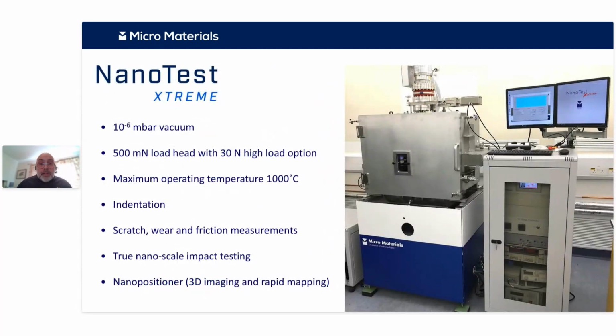That's a rather better picture of our system in the vacuum. Some of the work that you'll see today has been done in that. Some of that's been done on the Vantage system, often with the purge chamber option. But what I want to emphasize here is that it's a full indentation system inside the vacuum, working up to 1,000 degrees centigrade. Indentation, scratch, wear, impact. It's a full system in there. It's not a modified SEM type of indenter, and we can put the nano positioner, we can scan and everything inside there.